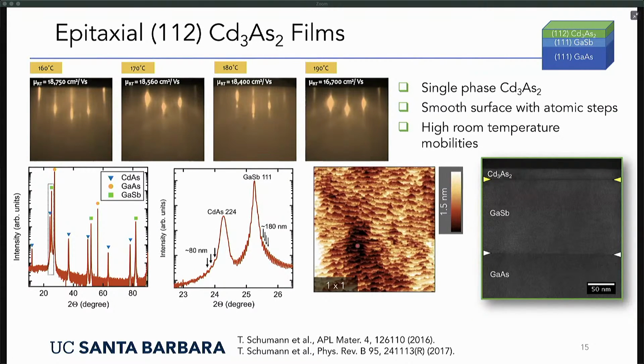These are some early results of the growth of cadmium arsenide thin films in the 112 direction. As I mentioned, this is the easy growth direction for cadmium arsenide. What you can see here are the growth temperatures. They're very, very low, so it grows at very low temperatures. It grows very nicely, which you can see. You can get streaky RHEED, you can get thickness fringes, and you can get atomically stepped surfaces in this growth orientation. This is a cross-section TEM image here on the right. You can also get fairly thin films of cadmium arsenide.